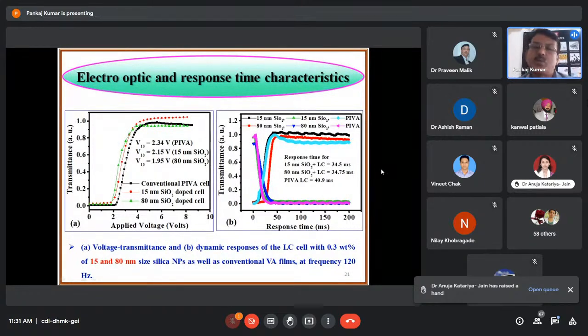So I am not saying that the silicon nanoparticle is the best one only and PIVA is not a good one. As you can see here, the response time is still fast as compared to the PIVA cell. Here 40.9 millisecond, but in case of the silicon nanoparticles, 34.5 millisecond. So it means that the silicon nanoparticles give some particular angle, which is called the pre-tilt angle, to the liquid crystal molecules. And if liquid crystal molecules have a fixed pre-tilt angle, that's why the response time may be fast when we apply the field.